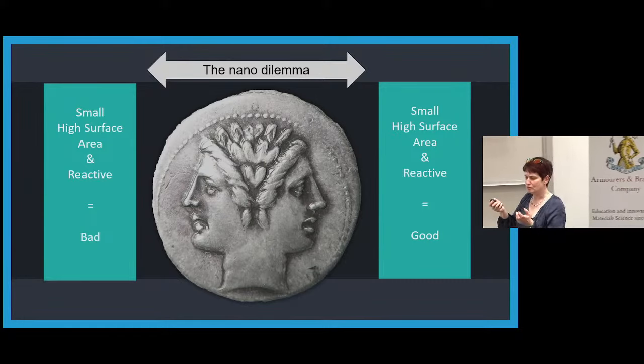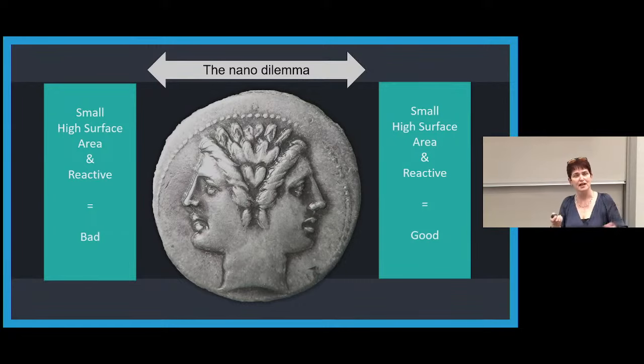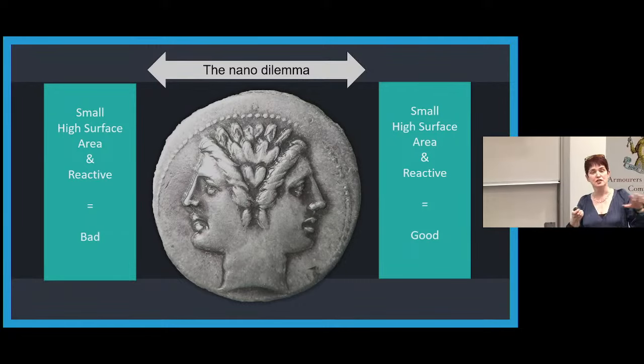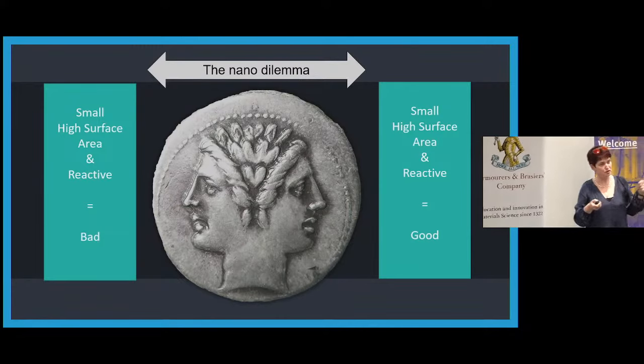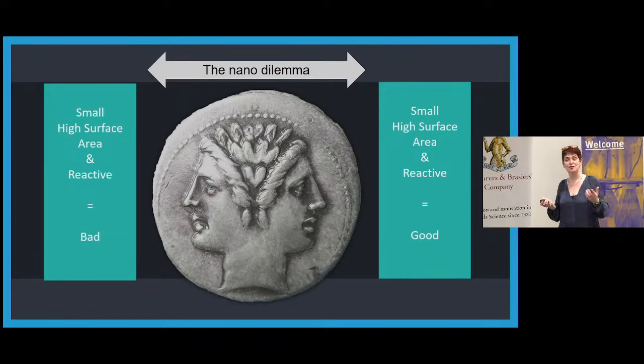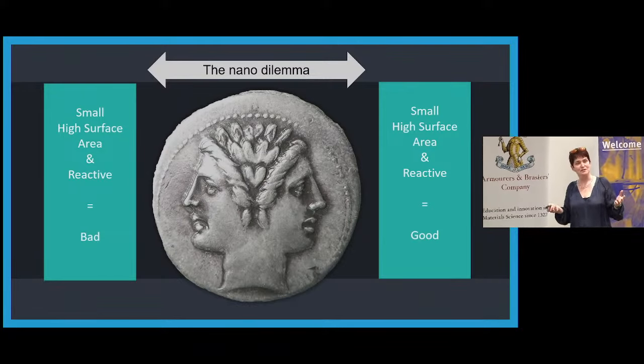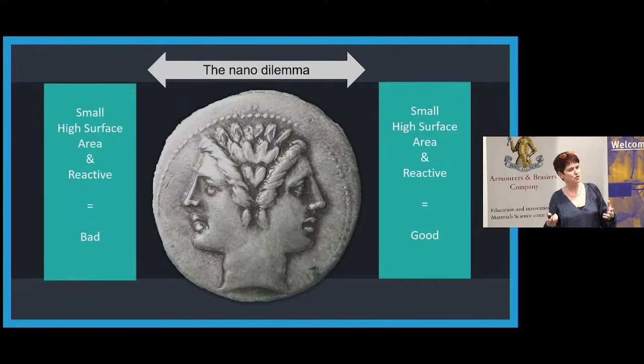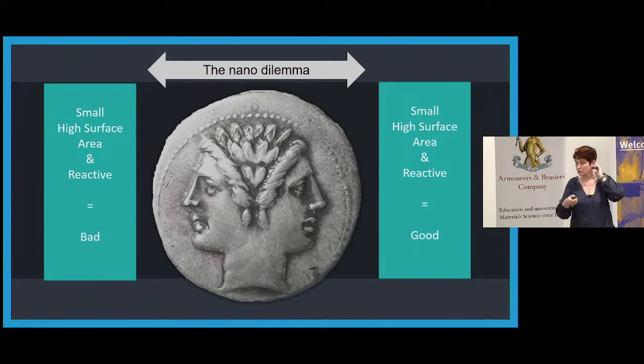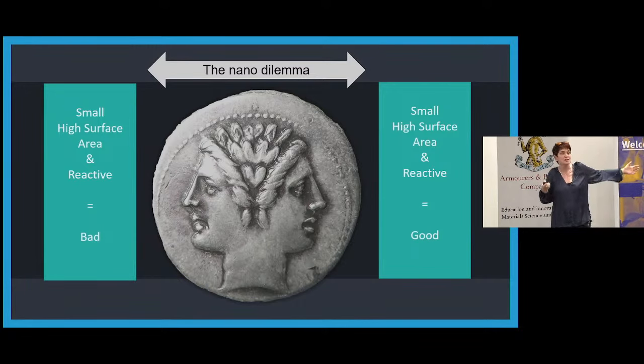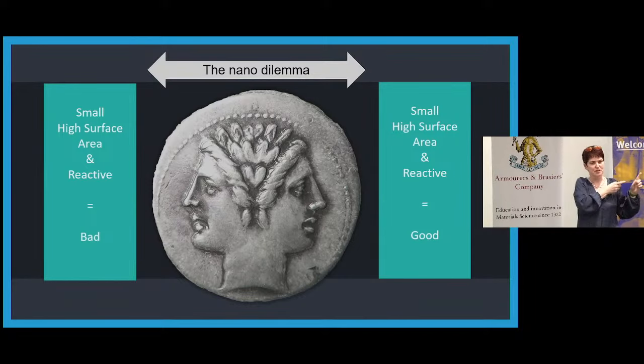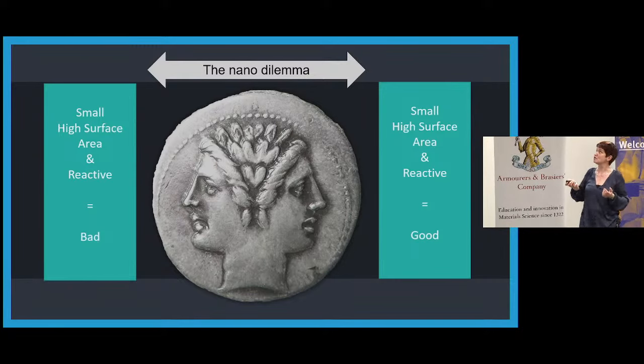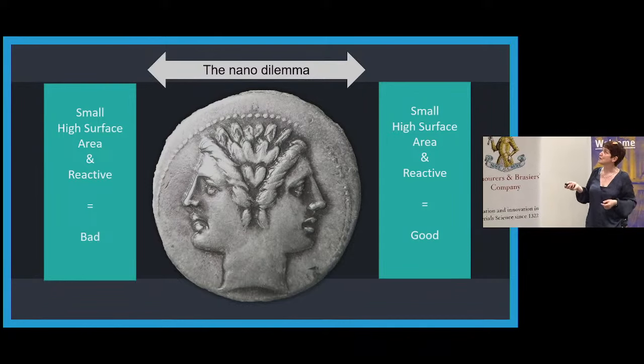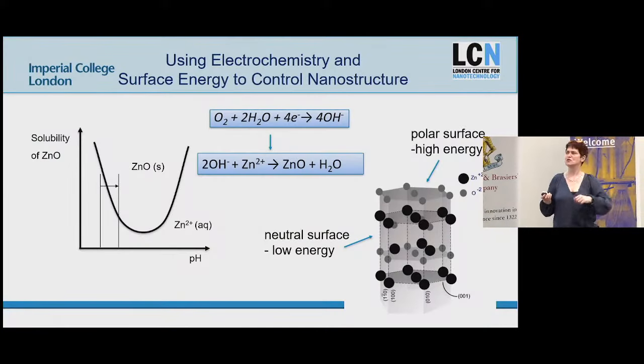However, if they're small, they can get to lots of places. They can get to places like across cellular membranes. They can get into the environment. They can get into the food chain because they're small enough to cross barriers that bulk materials don't, and they're harder to capture and filter out. They've got a high surface area and they're really reactive, so that means they're unstable. Right? They are wanting to grow. They are wanting to be oxidized or grow into structures that are not what you designed them for. So the things that make them really useful as nanomaterials are the things that make them potentially dangerous and unstable. So you've always got this development versus responsibility paradox almost, or the nano dilemma, as I like to talk about it. And we're going to talk about some of those issues in the next 20 or so minutes.